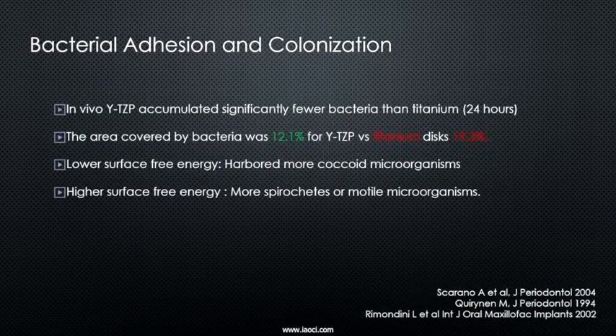But if you have a surface that tends to be a little rough, because highly polished titanium is never as smooth as a polished ceramic. And plus it's charged. It has charges in it. So it's always going to attract and retain bacteria and plaque. That's the reason why. And there was a study done by Rasperini, and Scarano replicated it also.